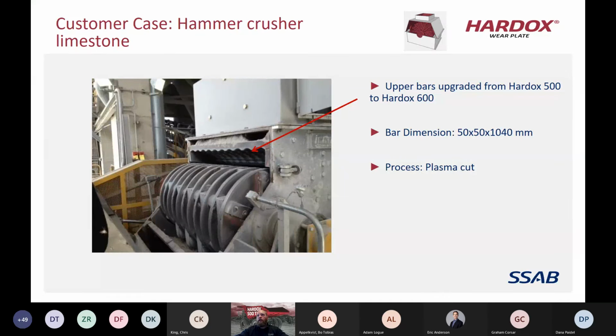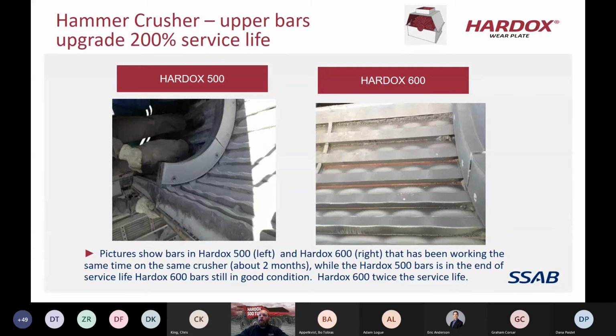And then another one is a hammer crusher for limestone. Basically they upgraded the wear bars from Hardox 500 to Hardox 600. They were 50 by 50 millimeter, so basically 2-inch by 2-inch, and they were cut by plasma. The Hardox 600 pretty much doubled the wear life. If you look at the picture on the left, you see how the bars have been worn quite a bit, and the Hardox 600 still looks very good. So they're estimating about double the service life going from the Hardox 500 to 600.